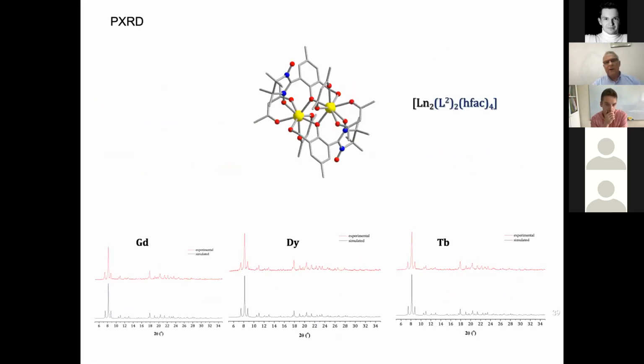And to be sure that the crystalline phase is pure, together with the elemental chemical analysis, we are now sure that we have the desired compound. The desired compound is binuclear, and the two lanthanide ions are connected by a phenoxido group. The nitronyl nitroxide moiety acts as a monodentate ligand towards each lanthanide ion. And in these structures, the two NO groups are coplanar. So the oxygen atom is out of the pentaatomic ring only in the crystal structure of the ligand.